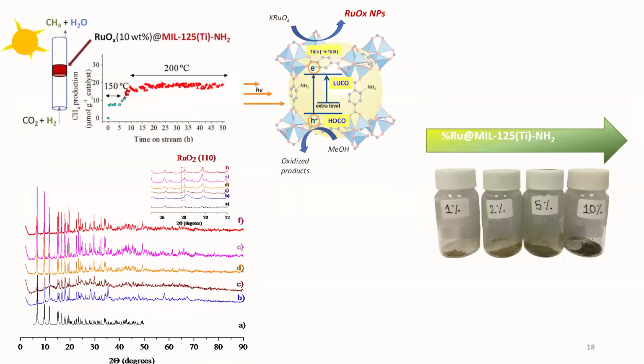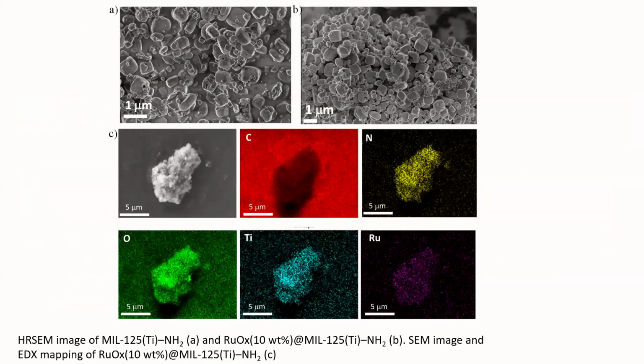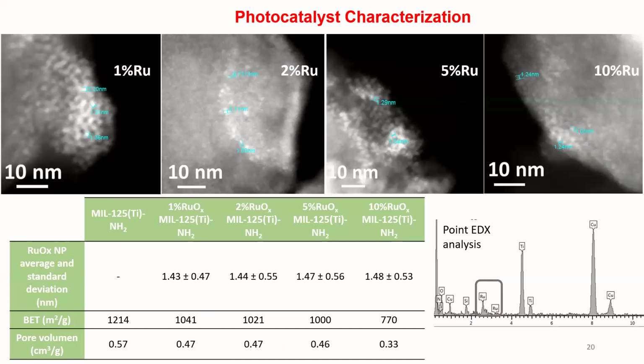So we took MIL-125 titanium amino. We loaded a ruthenium-based catalyst with different weight percentages, and it was characterized by powder XRD, and again by SEM analysis. And this is a TEM analysis. Here I just wanted to conclude that upon increasing the loading of ruthenium, the particle size was more or less the same, it did not increase much.